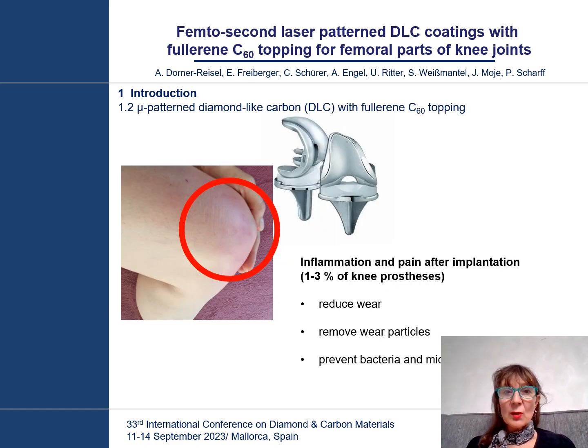Wear particles are a major cause for inflammation in artificial joints, for example knee joints. In fact, 1 to 3% of all implanted knees suffer from inflammation. This is strong pain for the patient, and this problem can be faced if one increases the wear resistance, so reduces the wear, removes the wear particles, and prevents inflammation by reduction or prevention of bacteria and microbe growth.